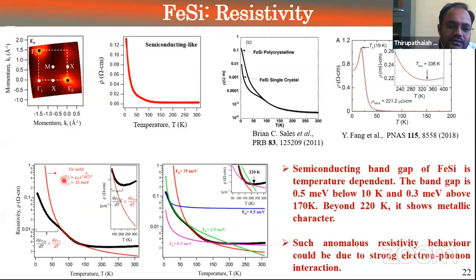Then we started fitting the activation formula, temperature range by range. First we fit between here and here, between 70 and 170 or 150. Here we got around 35 meV. Then we kept on changing the range and fitted using this activation formula. As we go close to 10 Kelvin or so, the energy gap is decreasing, and it is almost negligible, 0.5 meV. Also as we go away from 150, the energy gap is becoming even lesser than that, 0.3 meV. And at around 220, this in fact becomes metallic resistivity. So that clearly explains why we don't see a gap there, and also that this is not indeed an insulator or semiconductor. It depends at what temperature you measure it.